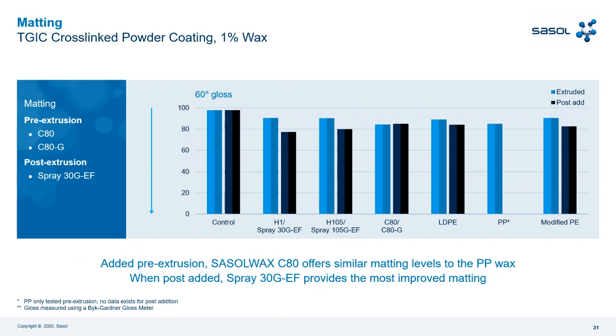In pre-extrusion, we tested all the waxes that I mentioned before, but C80 and C80G achieve the best results. So you can see here the Sasol Wax C80, in this case pastillized form, and also Sasol Wax C80G achieve a very good result. In post-extrusion, we have Sasol Wax Spray 30 GEF, again like before, that achieves a nice result. In this case, in pre-extrusion, C80 works similar to PE wax or to the HDPE wax. And in post-extrusion, we have Sasol Wax Spray 30 GEF that is a little bit better with respect to the other products.